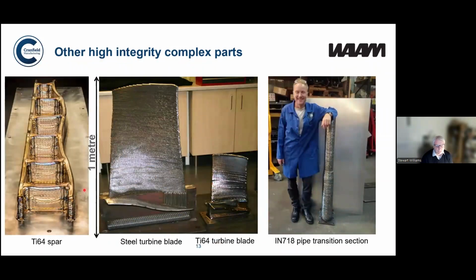However, we then went on to build many other parts. This is just a few examples here. So the one on the left was a part we made for BAE Systems a long time ago now. And then the ones in the middle are large-scale turbine blades for GE. And the one on the right is an oil and gas part. It's quite a simple part, as you can see, which is just an Inconel transition section. But these are actually rather difficult to manufacture in practice.